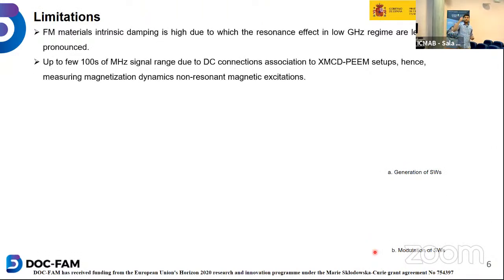Ferromagnetic materials have intrinsic damping for sure, due to which the resonance effect is quite low. The effects are in gigahertz regimes. Our system, the XMCD-PEEM, usually, due to the DC connection in the XMCD-PEEM facilities, can reach only hundreds of megahertz, and hence we are measuring non-resonant magnetic excitations. So actually, we are not measuring magnetization dynamics at the intrinsic frequency of the ferromagnetic material.